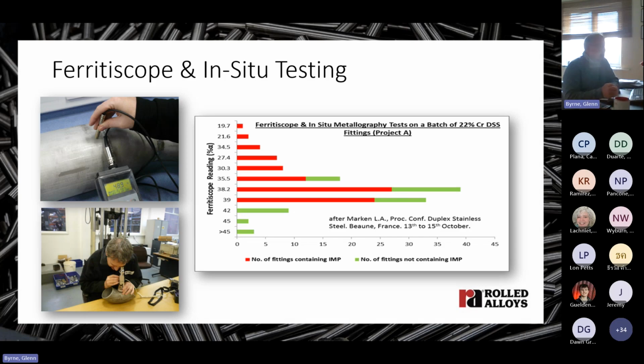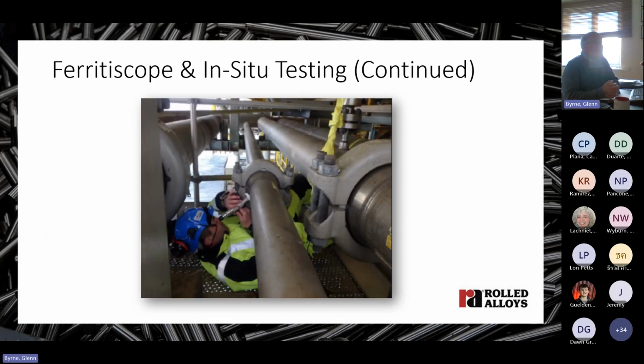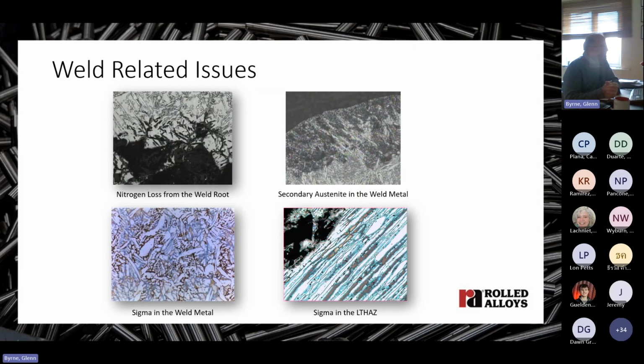Now, some oil companies specify ferritoscope testing in addition to microstructure, corrosion and impact testing, and I consider that to be good practice. It's easier, less costly and less disruptive to do this and pick up any problems early rather than after fabrication installation, where this type of testing can be a painful experience, as you can see in this particular slide. So now let's talk a bit about welding related issues.